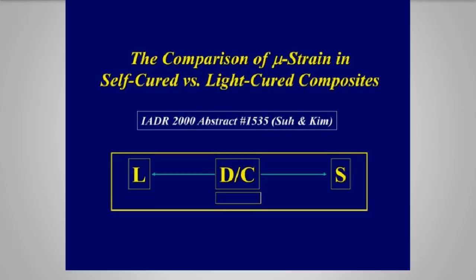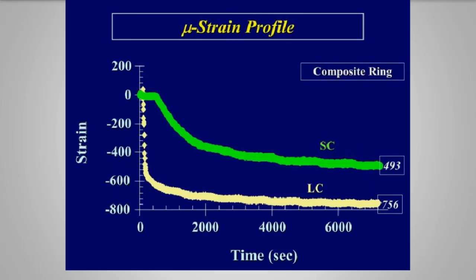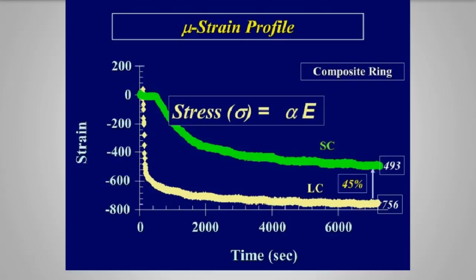So if you look at a paper in 2000 by Dr. Suh about light cure, dual cure, and self-cure, and what is the difference in the strain and shrinkage, it kind of says it here again, is that you're going to have less stress with a self-cure, dual cure material than you are potentially with a light cure, according to the clinical indication. Again, the volume of clinical cases we do are going to be generalized incremental layering. However, when you cross the line where you have to get into managing stresses, then you're going to look at self-cure or dual cure materials to help you reduce the sensitivity issues, 45% less, in fact.